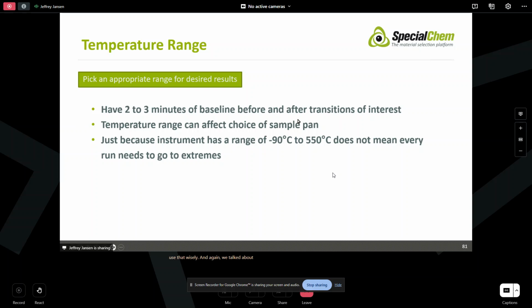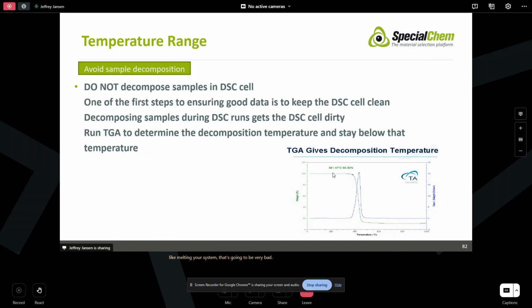And again, we talked about sample pans. If you're going to go very high in temperature, understand that you don't necessarily want an aluminum pan that might melt in your system. That's going to be very bad. One thing about temperature is that you don't want to decompose the samples in the DSC cell. The more decomposition that you undergo in the DSC cell, the more contaminated the thermocouples are going to get, and you're going to get poor contact. You're going to see your signal diminish. You're going to see your results get wonky. So again, you don't want to take a material through decomposition.